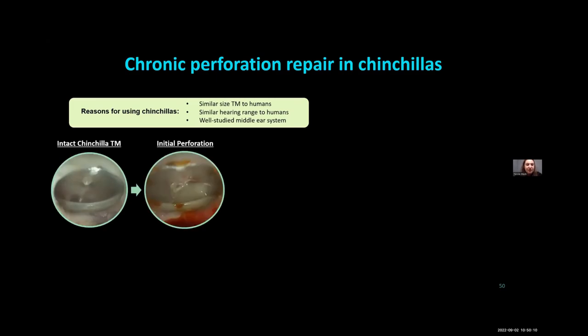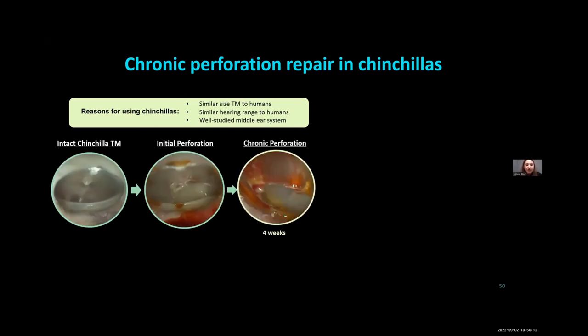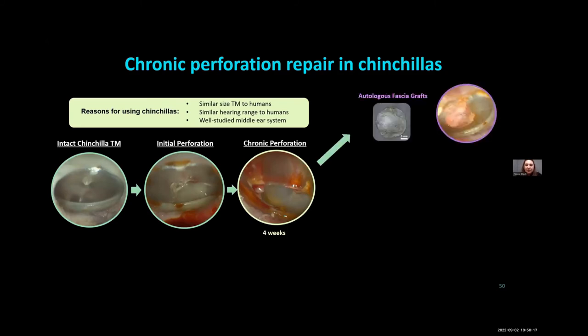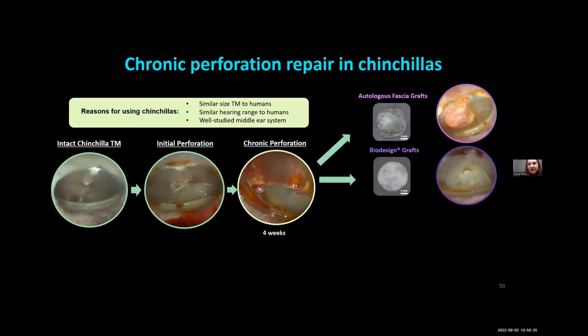So we take these chinchillas, we create a perforation in their eardrum and wait about 2 to 4 weeks to make sure it's chronic. And then we can repair it with different graft materials. One of which is the autologous fascia. This is what I mentioned is commonly used as the standard of care, harvested from the chinchillas.